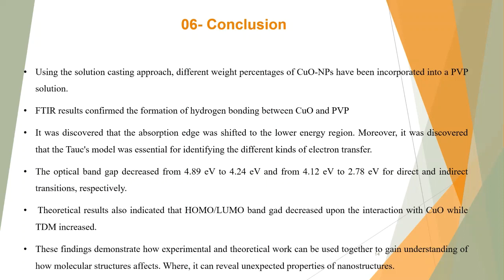Theoretical results also indicated that HOMO-LUMO band gap energy decreased upon the interaction of copper oxide with PVP, with increasing total dipole moment values. These findings demonstrate how experimental and theoretical work can be used together to gain understanding of how molecular structures affect properties, where it can reveal unexpected properties of nanostructures. Also, these results confirm that the prepared solutions of PVP and copper oxide can be used as a protective layer in the food packaging industry or in the sunscreen industry.